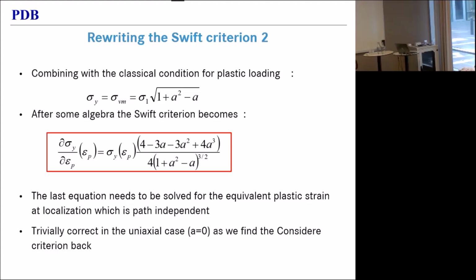Now you can immediately see that it's consistent. In the uniaxial case, when A is equal to 0, that whole multiplicative factor becomes unity, and you end up with the Considère criterion. So you fall back on something you know, you fall back on your feet.